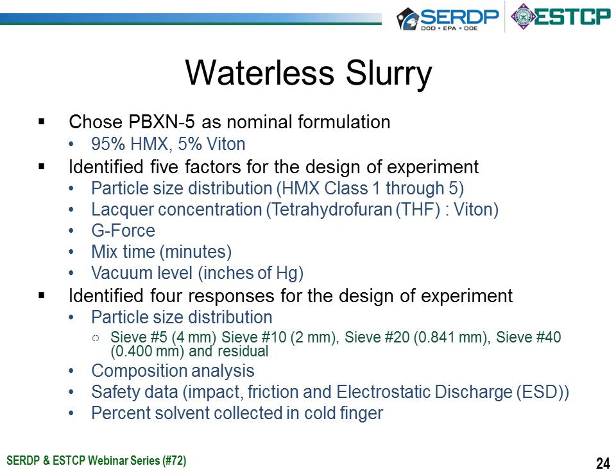We chose PBXN-5 as our nominal formulation. PBXN-5 is 95% HMX and 5% Viton. Viton is a fluorinated thermoplastic polymer. We identified five factors for the design of experiment. We looked at particle size distributions utilizing different combinations of class 1 and class 5 HMX. We looked at different lacquer concentrations. We used tetrahydrofuran to dissolve our Viton. We were looking at different lacquer concentrations of tetrahydrofuran to Viton.